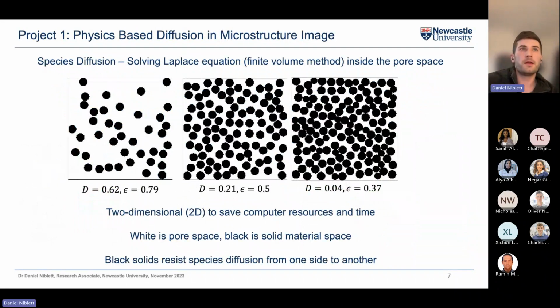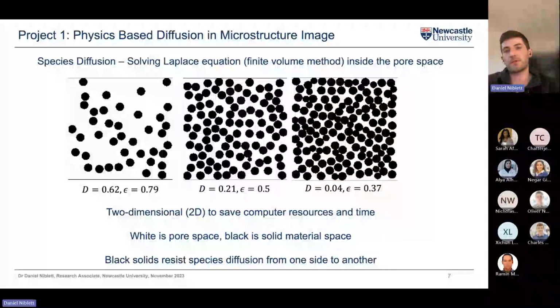So to start off with, what I needed was a physics-based simulation which would characterize an image of some type of porous material. So an example here is solving the Laplace equation. We're using the finite volume method inside the pore space of this 2-dimensional porous structure, where the black circles represent the solid particles and the white space in the box around is the pore space or the void space where species can diffuse through that space. And the black solids essentially resist species diffusion from one side of the material to the other, and you want to try and minimize that resistance.